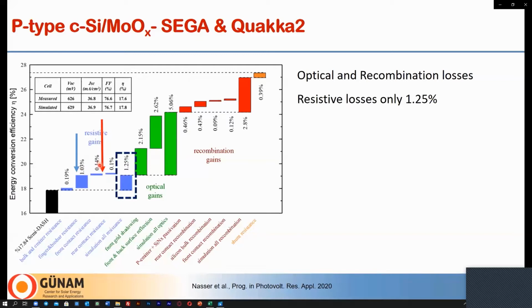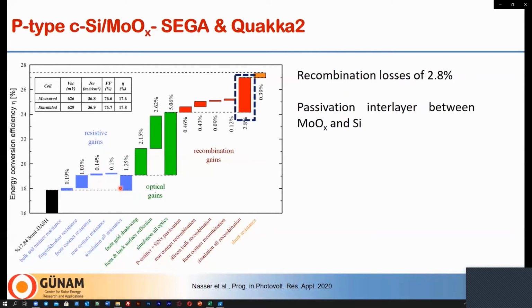The rear contact resistance, which is composed of our molybdenum oxide silver, is the smallest contributor with only 0.1%. And this is expected because we measured very low contact resistivity from molybdenum oxide silver on P-type wafer. Also, the second dominant loss, which arises from recombination, especially at the backside, can be avoided by using a passivation interlayer between molybdenum oxide and silicon, or by further optimizing the front side doping and silicon nitride passivation recipe.